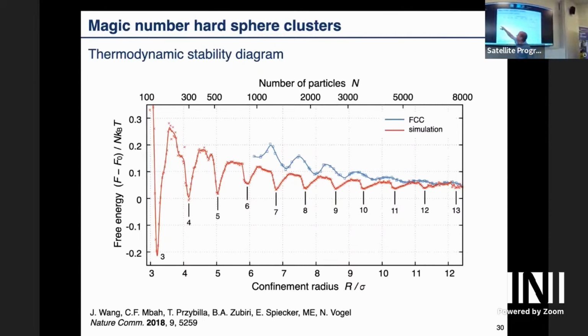And this is the free energy per particle. So we see that the difference we had to resolve is like in the tenths of kT range in free energy, and even here like hundredths of kT. So pretty small free energy differences, but we do see these magic number oscillations.